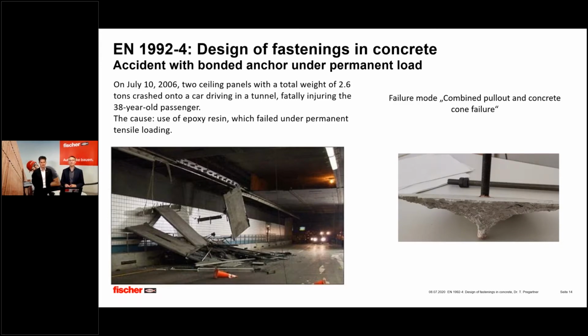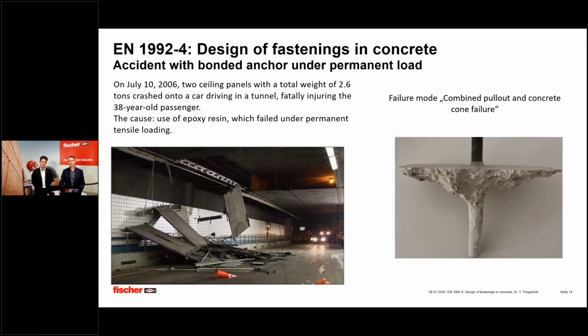Adhesive anchors have one speciality. They have a special failure mode, which is called combined pull-out and concrete cone failure. Adhesive anchors have a variable embedment depth between 4 times diameter and 20 times diameter. You have a very flexible range to choose your anchorage length, and coming with that, they also tend to change their failure mode, either with increasing embedment or with reducing bond strength. On the photo on the right, you see an adhesive anchor with a high bond strength and a low embedment, and you see a beautiful concrete cone failure, and the anchor was able to activate the full concrete cone until the end of the anchor rod.